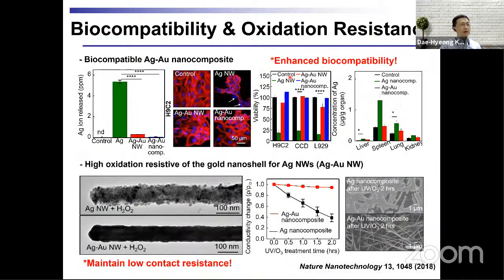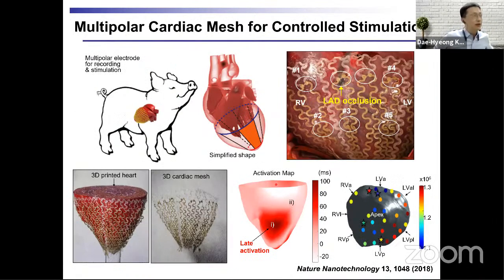And we confirmed the biocompatibility through in vitro experiments as well as in vivo animal experiments. And due to the gold shell coating, we could prevent oxidation of silver nanowire, so we could maintain the initial conductivity over a long period of time. And by using this material, we fabricated a multi-channel cardiac mesh designed for the pig heart. We first imaged the pig heart, made a model, and customized the design of the multi-channel cardiac mesh as shown in this image. Since we were interested in the local EKG recording as well as the local electrical stimulation, we paired two electrodes into one channel.